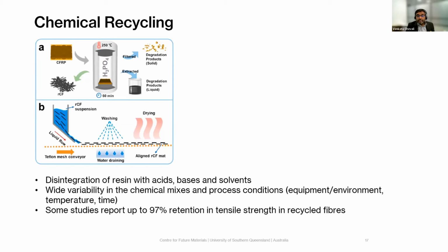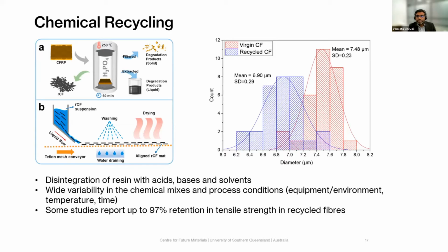So thermal recycling in some cases produces monomeric or oligomeric products, whereas chemical recycling also has the capability of producing degradation products, which you would say are not really useful in an engineering sense. So in a chemical recycling method, you would look at disintegration of resin with acids, bases, and solvents, and you can have up to 97% retention in the tensile strength versus the virgin carbon fibers.